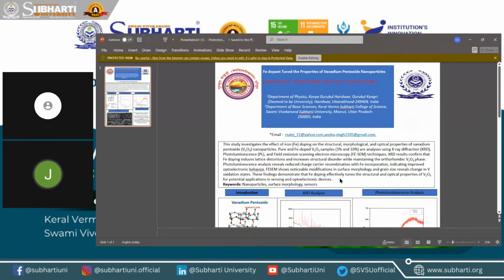Pure and Fe-doped V2O5 samples, 3% and 10%, are analyzed using X-ray diffraction (XRD), photoluminescence (PL), and field emission scanning electron microscopy (FESEM) techniques. XRD results confirm that Fe-doping induces lattice distortions and increases structural disorder while maintaining the orthorhombic V2O5 phase. Photoluminescence analysis reveals reduced charge carrier recombination with Fe incorporation, indicating improved optoelectronic behavior. FESEM shows noticeable modification in surface morphology, and grain size reveals changes in V-oxidation states.